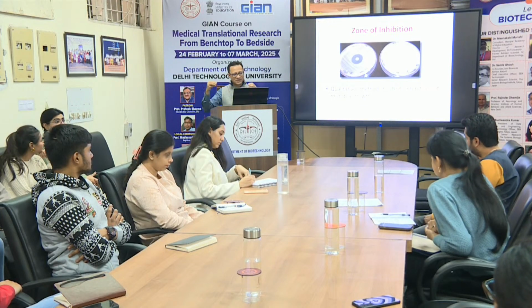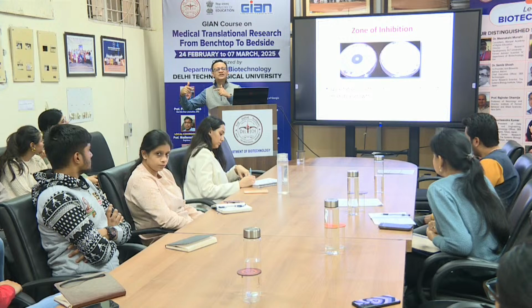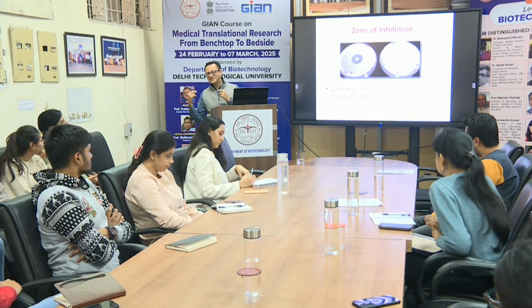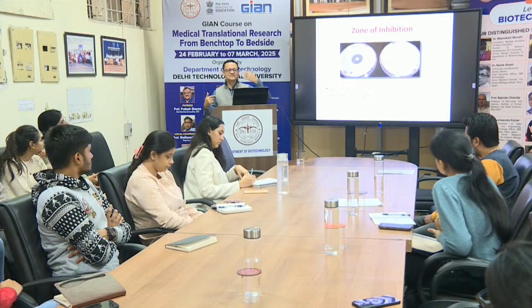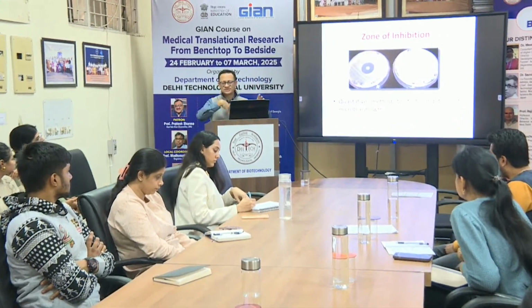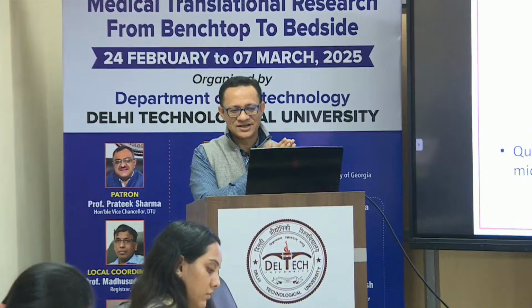You keep it for 1 month and then repeat a 24-hour study again. So basically you are mimicking the release in buffer, 7.4, 37 degrees for 1 month, and seeing whether even after a month you are still releasing drug to keep it antimicrobial. You can do that, but in reality it's going to be sitting in blood, now it's sitting in buffer. It's not the most accurate way.